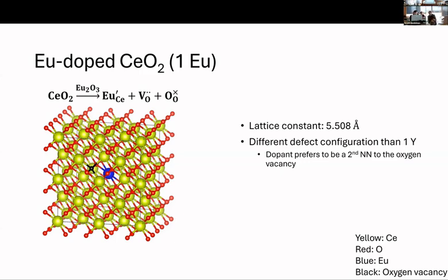Question, more like a comment, and I don't know if this is necessarily related to what you see in negative CeO2 constant, but if you look at Born stability criteria, that also kind of suggests the same thing. So for less symmetric materials, as your C11 goes from positive to negative, then you have a crystal in an unstable state.